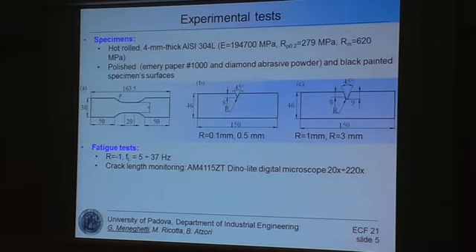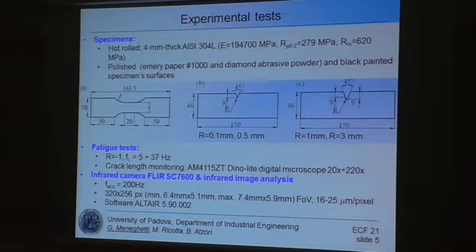Fatigue tests were run in completely reversed loading, applying a load frequency between 5 and 37 Hz. The crack length was monitored by means of a digital microscope, and the thermal images were captured by means of a FLIR SC7600 infrared camera. Thanks to an extended ring, we reached a geometrical resolution of about 16 to 25 microns per pixel.